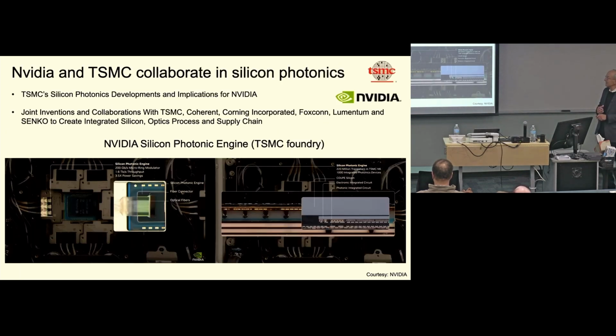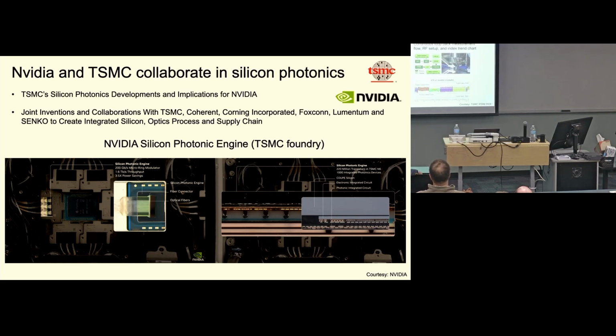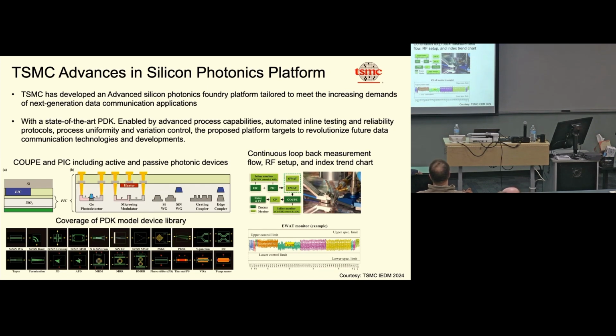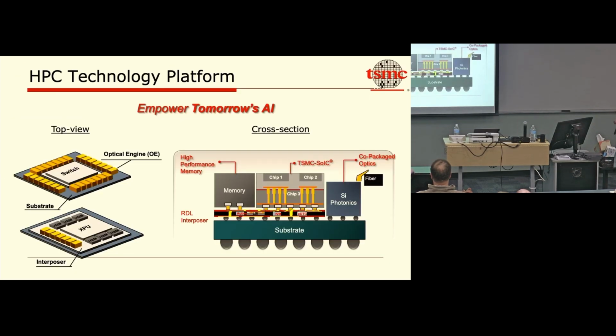The other big announcement they made is that, of course, they're using TSMC for the silicon photonics. So again, there's lots of foundries that do silicon photonics, but TSMC is sort of a latecomer to the game, but obviously they're the elephant. And of course, NVIDIA is going to use them because all the electronics is made by TSMC. And so that's the other big excitement coming out of it. And again, they're doing all the same vertical integration of electronics and photonics, just using copper bump bonding between those two. And so again, the field's moving extremely fast. This is a little more detail on it, but again, they're showing the same thing. We've got an electronic chip with all the photonic chips around it, and then all these are plug-in fibers, right? So the whole issue is how do you get the yield high enough to make this happen?